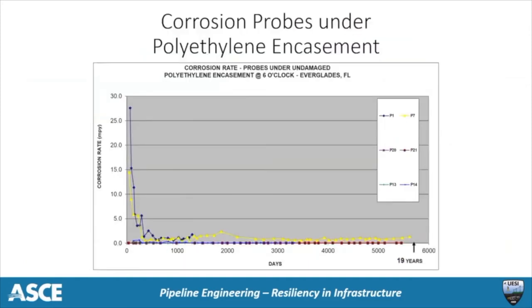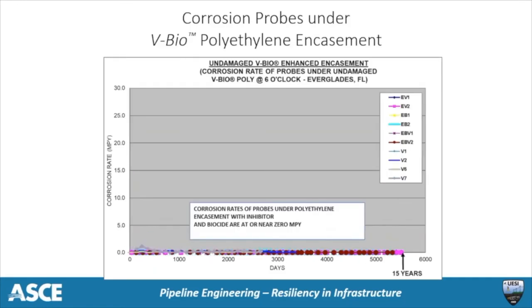Here we see the plots of data from one of our member companies' tests on traditional polyethylene film, such as the film found in Lafourche Parish. At the beginning, corrosion rates were registered that were very high, but diminished over time to very low rates. This would account for the superficial oxidation that we saw earlier, but over time the readings became very low to the point that the corrosion rates were measured at 0.7 mils per year. NACE considers corrosion to be under control when the corrosion rates are 1 mil per year or less.